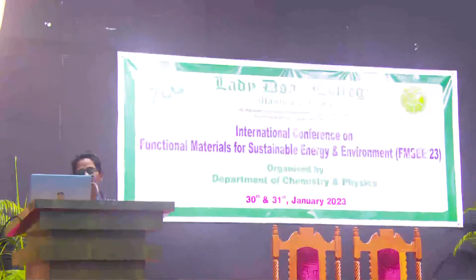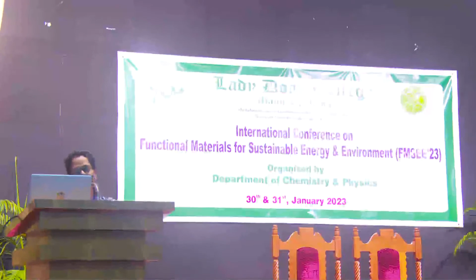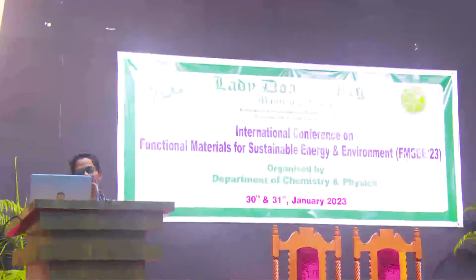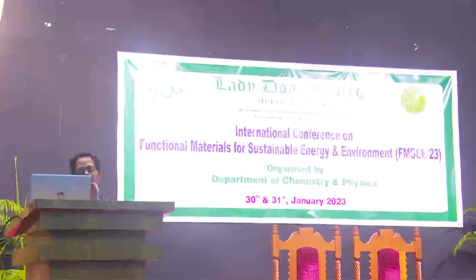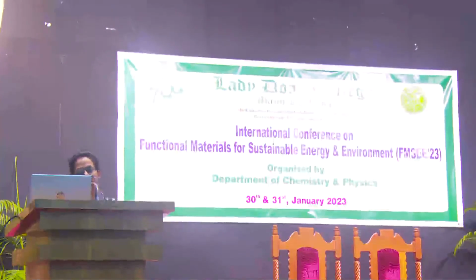On doping Fe, the peak shifted to higher angle, the crystalline size decreased, and the microstrain level and the dislocation density increased. In the Raman analysis, a prominent peak is observed at 351 cm inverse. It belongs to the trigonal copper barium tin sulfide phase, and all the other peaks are binary secondary phases. The peak at 200 cm inverse belongs to barium sulfide, 142 cm inverse belongs to tin sulfide binary phase, and 473 cm inverse belongs to copper sulfide binary phase, in both copper barium tin sulfide and Fe-doped copper barium tin sulfide.